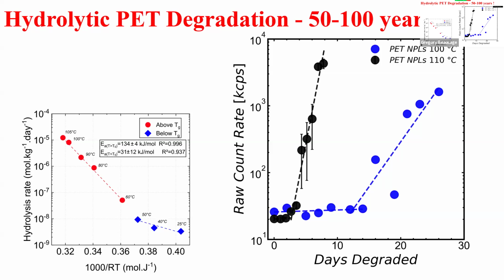This is data for PET. I showed you before 110C, 100C. Somebody went through and measured reaction kinetics for the degradation of PET as a function of temperature. Okay, and if I take my 2 data points, put it up there, it follows exactly the time-temperature superposition. Why am I seeing a break here? Anybody know in this curve? This is PET degradation by water.